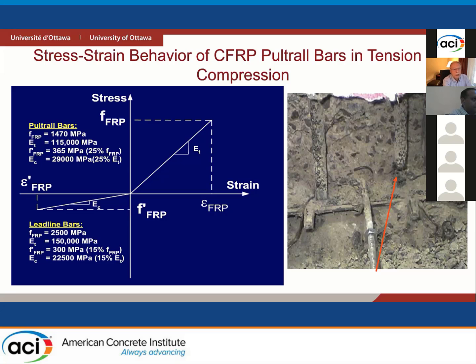Here on this diagram, you see stress-strain relationships in tension and in compression. In tension, we went all the way up to the rupturing strain, and in compression, we were able to buckle the reinforcement. Tensile tests were conducted as we typically do, with ends embedded in steel tubes with sufficient bond length to be able to break the specimens. For the compression tests, we took smaller samples and crushed them in the machine, and we were able to see the kind of buckling that was observed in our column tests.